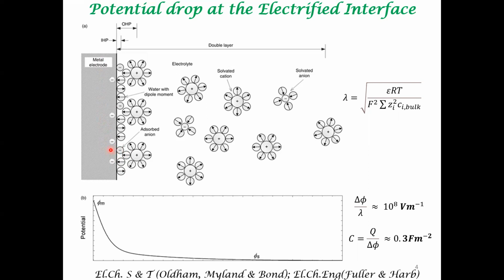Therefore, the capacitance is also greater. Such a strategy is utilized in the case of, let's say, carbon electrodes. You can form very highly porous structures from carbon typically. These are called aerogels and so on. And even for metals, you can have porous structures, foams. For example, nickel foams will have very high electrochemical surface area, and that would help in increasing the capacitance.